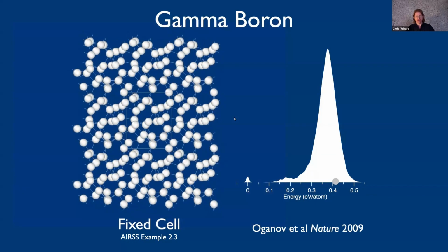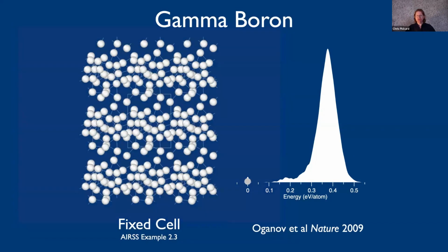So as we do that, it starts off looking random and it ends up looking random. This is a lower energy local minimum that still looks somewhat amorphous, so maybe this is like an amorphous phase of boron. But if we do this again, say over 200 times, then about 1 in 200 times we get this situation where an initial structure starts off looking rather random, but we do the geometry optimization, and if we wait long enough, eventually it clicks into this perfect crystal structure. It's a beautiful structure.